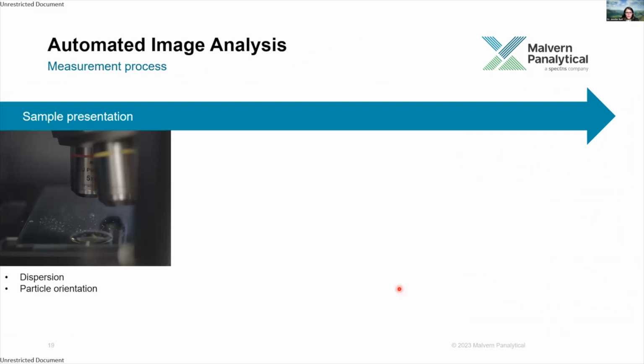So there's four key stages to a morphological measurement. The first stage is dispersing the sample, where we want a good dispersion of well-separated particles. And we have a range of different dry and wet accessories available, which allows us to look at our samples either as dry powders, as slurries, as suspensions. We can also look at samples on filters. These all can be analyzed.